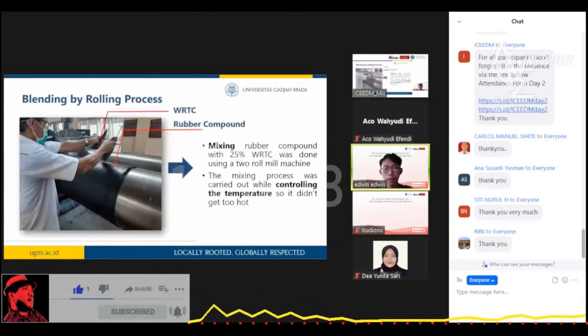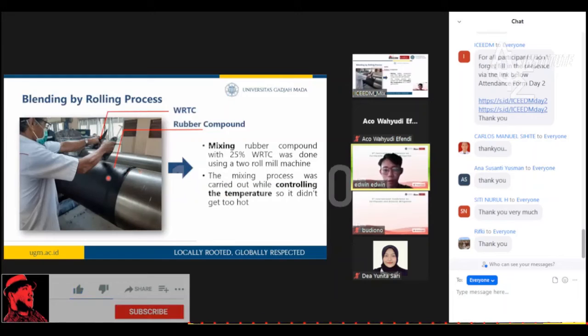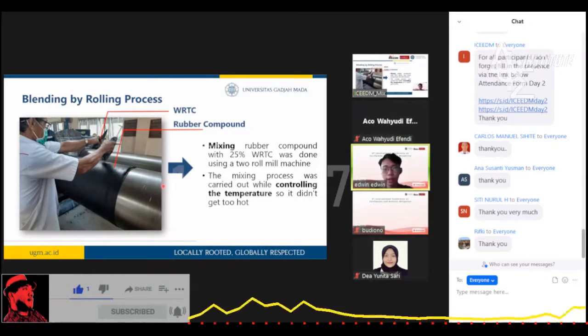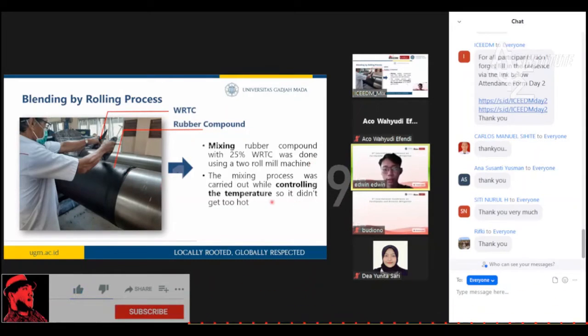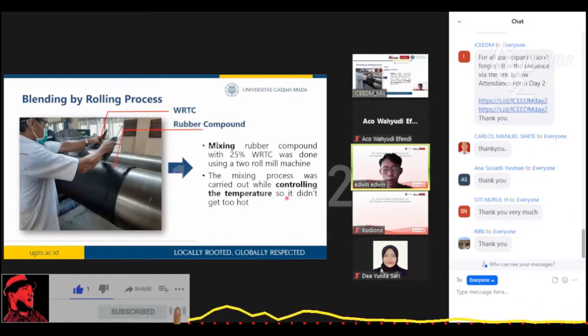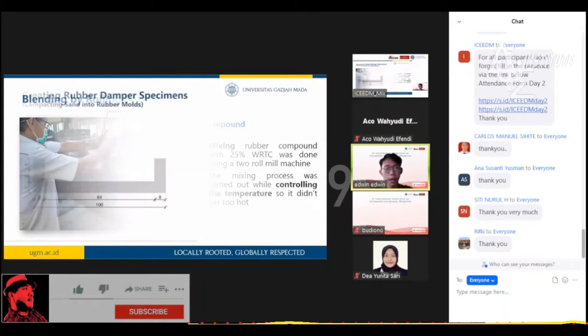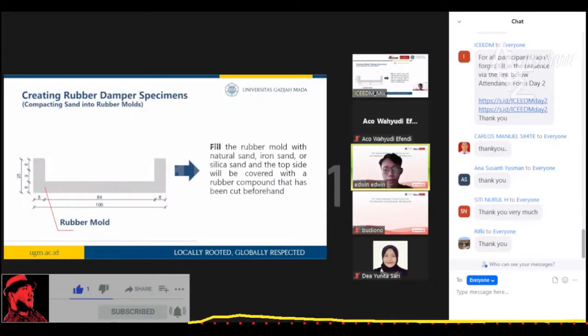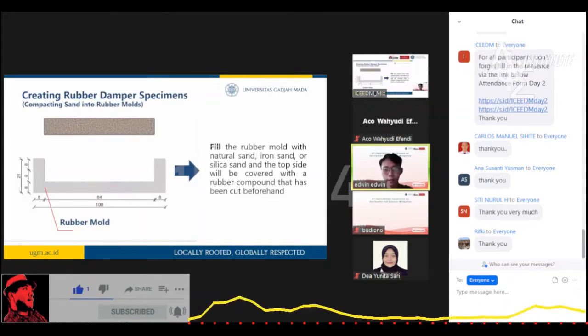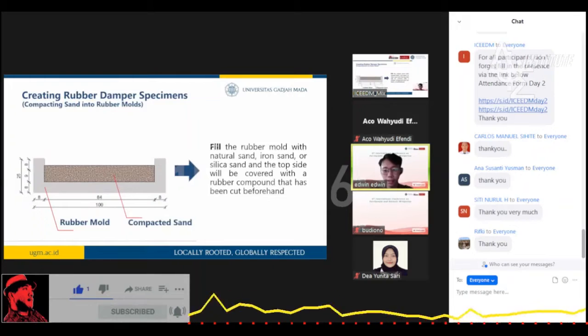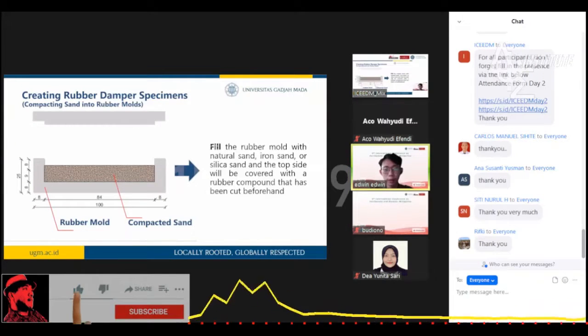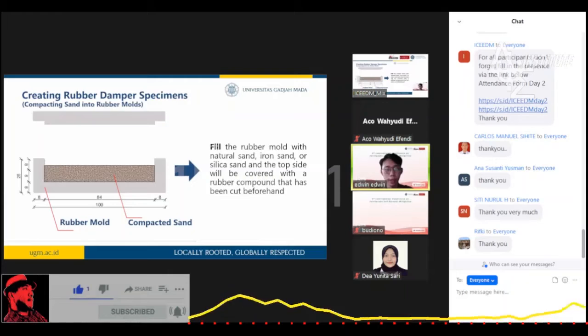The next step was mixing rubber compound with 25% WRTC using a 2-roll mill machine. And the mixing process was carried out while controlling the temperature so it didn't get too hot and reach the vulcanization temperature. After that, rubber mold was made and then filled with natural sand, iron sand, or silica sand, and the top side will be covered with a rubber compound, as we can see in the figure.